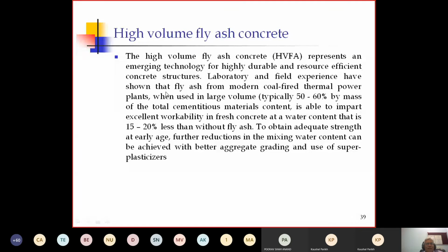Laboratory and field experience have shown that fly ash from modern coal fired thermal power plants, when used in large volume, that is in the range of 50 to 60% by mass of the cementitious material, is able to impart excellent workability in fresh concrete at a water content that is 15 to 20% lesser than without the fly ash. To obtain adequate strength at early stage, further reduction in the mixing water content can be achieved with better aggregate grading and use of superplasticizers. So basically in high volume fly ash concrete, we can go beyond 50 to 60% replacement of the cement. This can also be an emerging technology for getting highly durable and resource efficient concrete structures.